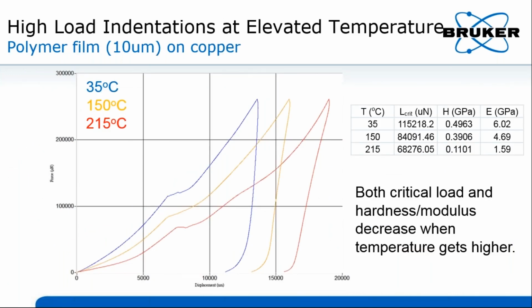Another similar example of indentation-induced delamination is shown here. The sample is a polymer film on copper sublayer. The temperature was chosen to be lower than its glass transition temperature of around 250 degrees Celsius. Therefore, the three temperature levels are set here from 35 to 215 degrees Celsius.